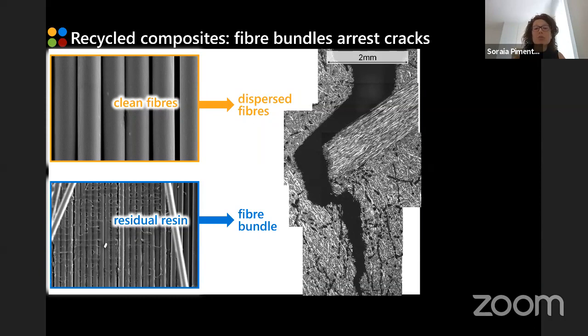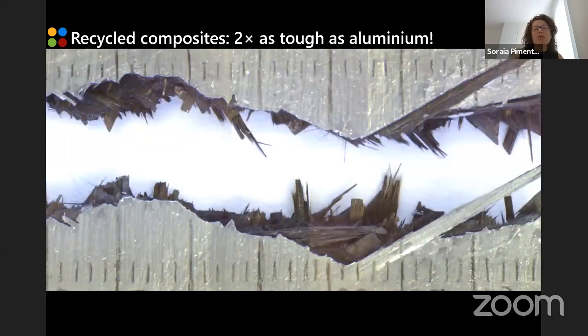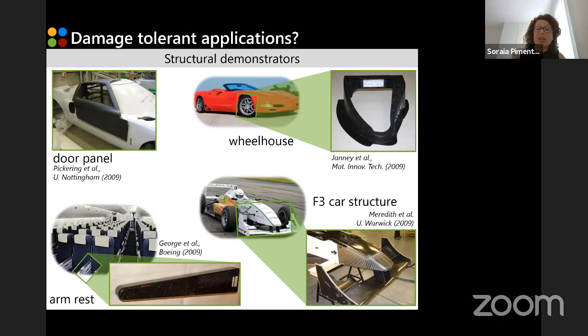So basically the opportunity that we have here with recycled composites is that if we make use of these fiber bundles, we can not only recover fibers with better properties because we are less likely to damage them during the pyrolysis process, but we are also able to get recycled materials which are twice as tough as aluminium. And that brings a possibility of creating damage tolerant applications in a wide range of industries.